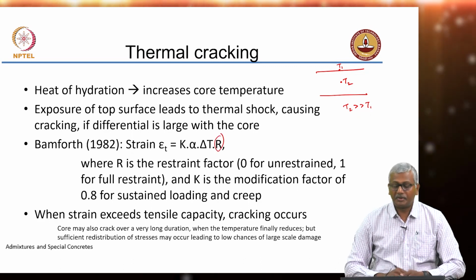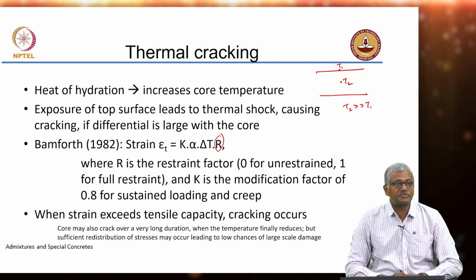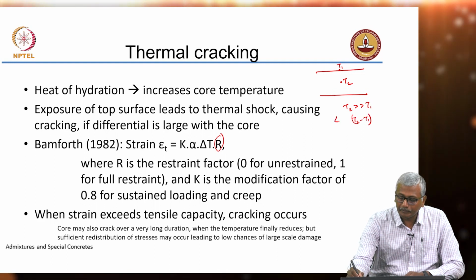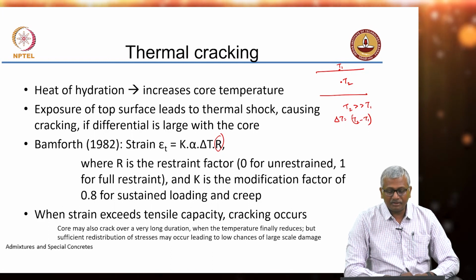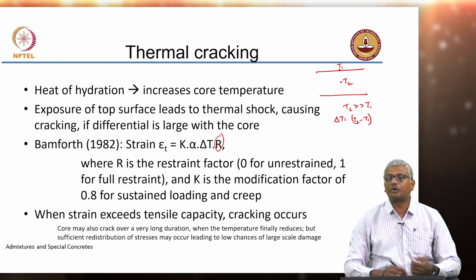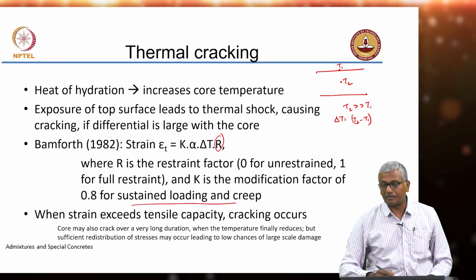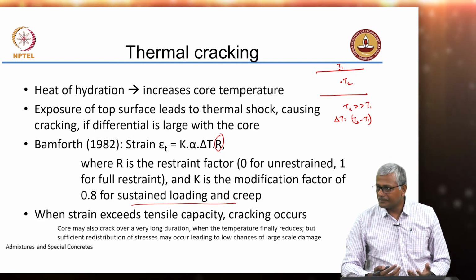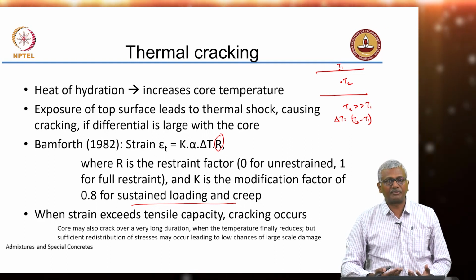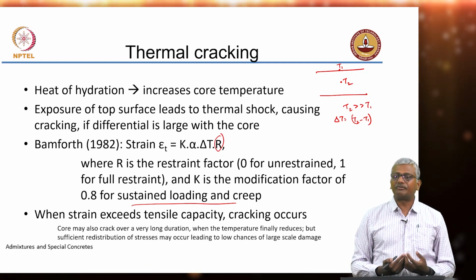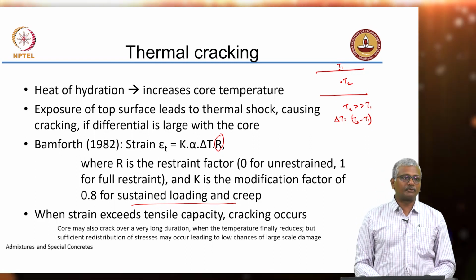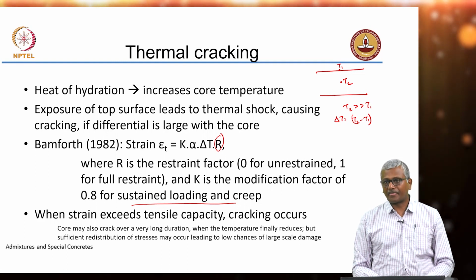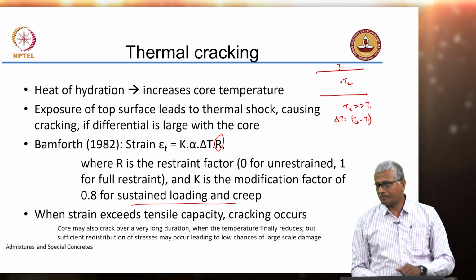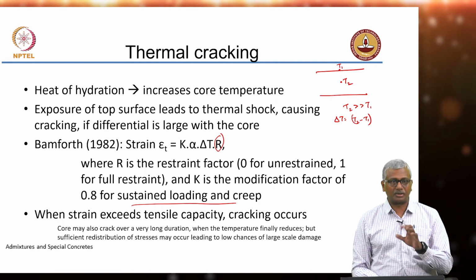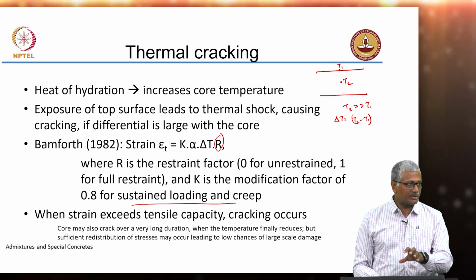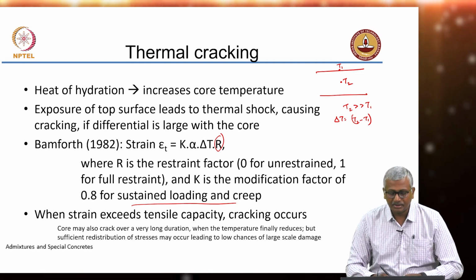R is the restraint. Depending upon the amount of restraint you have, you can calculate the thermal strain caused by this temperature difference T2 minus T1 as strain is equal to K into alpha into delta T times R, where K is a modification factor that accounts for the time dependency, modification factor for sustained loading and creep. See, this thermal shock does not happen instantaneously, right? It happens over a small period of time. To take into account the effects of redistribution of strains, you can lower the amount of strain that comes to your system by adopting this value K. So if K is 1, that means we are not considering the effect of time at all, right? We are considering thermal shock when K is 1, but in reality that is not the condition. So that is why this K factor is taken, and it is usually about 0.8 for sustained loading and creep.